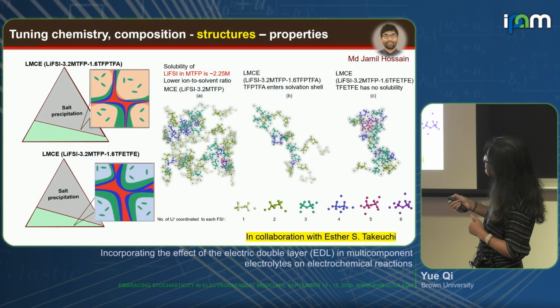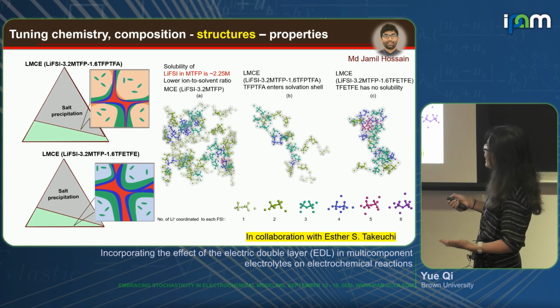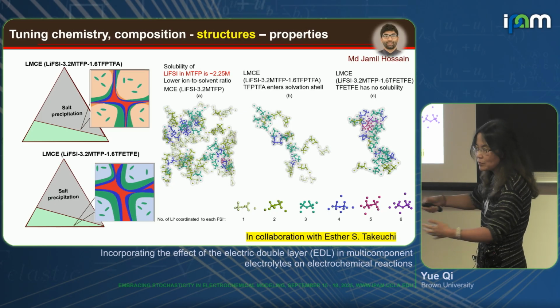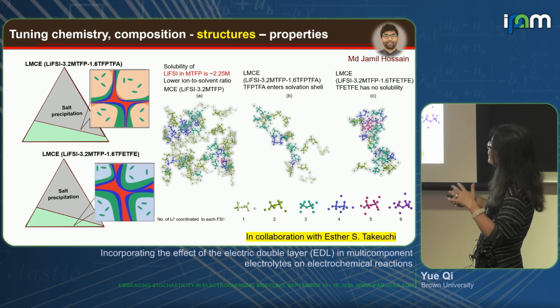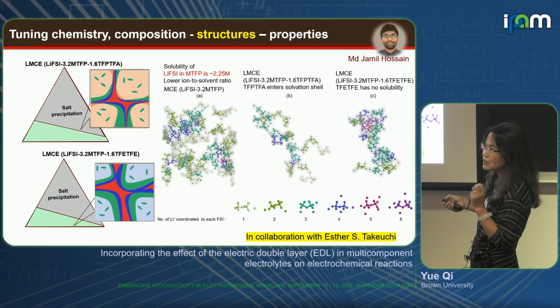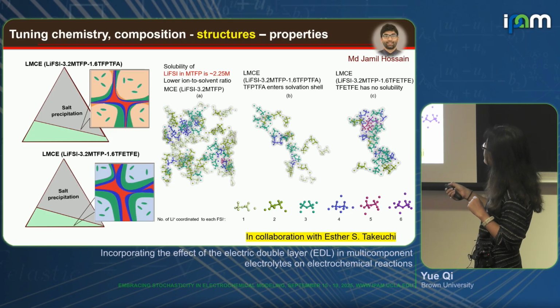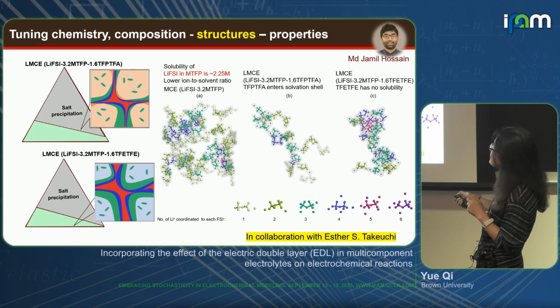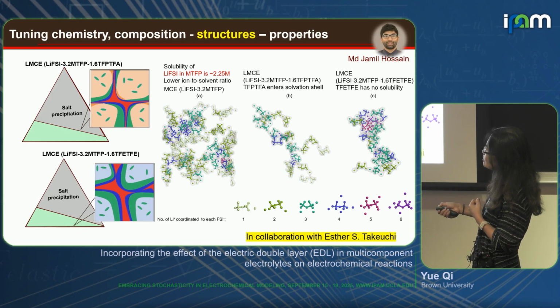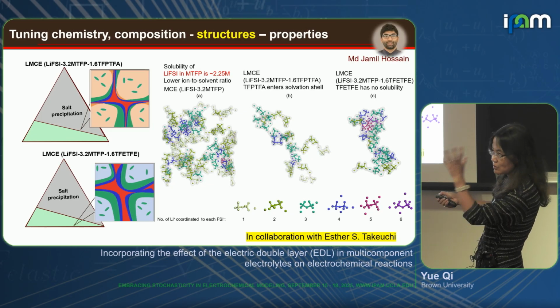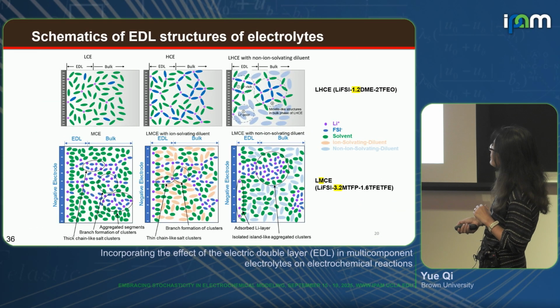This is a collaboration with Esther S. Takeuchi. And this is a fluorinated solvent, like everything's fluorinated. Solvents are fluorinated, additives are fluorinated, the diluents are fluorinated. But because the concentration is not 4 molar, it's about 2 molar, this is the maximum solubility we can achieve. And so they form more branchy types of salt clusters. It's not a cluster, it's like branches of salt. If you add one additive, you break those branches, but if you add another additive, you collapse those branches and form a cluster. That's because this diluent actually has zero solubility, and this one has some solubility, so they just act like a co-solvent, right? So here, we really want to plot and analyze our electrolyte in these 3 bins: salt, solvent, and diluent, based on solubilities. Right, so this is interesting.